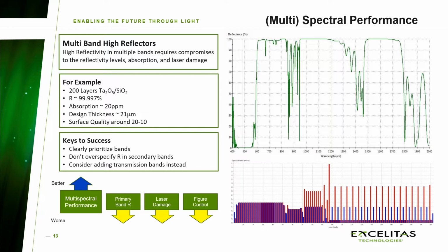it's a long deposition time. That actually introduces some compromises with laser damage as well, because there's more opportunity for defects to get introduced into the process. So the surface quality limitation may start to be an issue with a design of this length. So we have to prioritize the bands. We need to be careful not to overspecify the reflectivity. If you can deal with a lower level of reflectivity in some of the outlying bands and just focus on the primary band, you can typically optimize the trade-offs and get to a pretty acceptable trade space.